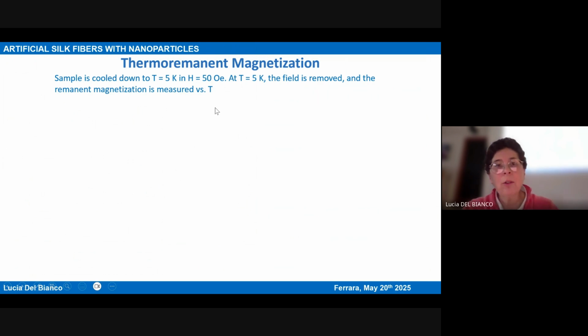And here we carried out a quite particular type of measurement. It's a little bit difficult, but I'll try to explain what we did. You take your sample, which in our case was a bundle of fiber. You put it into the magnetometer at 300 Kelvin, and then you decrease the temperature in the presence of a small magnetic field. When you arrive at the lowest temperature, 5 Kelvin, you remove the field, and therefore you obtain a remanent magnetization. And then you measure the remanent magnetization without field as a function of increasing temperature.